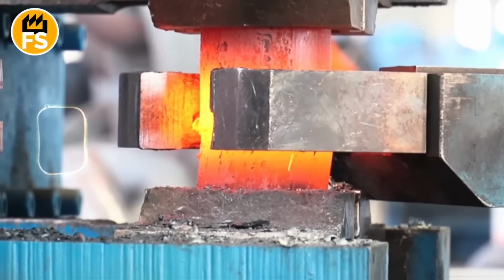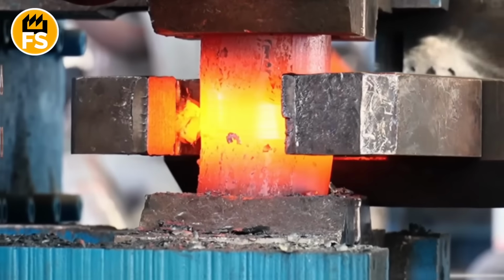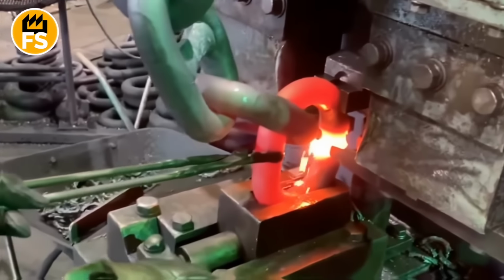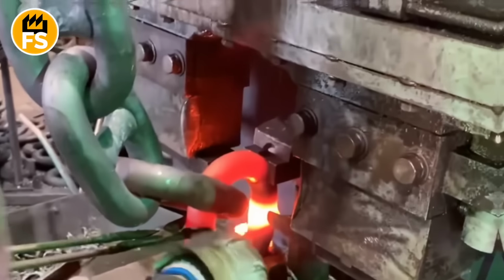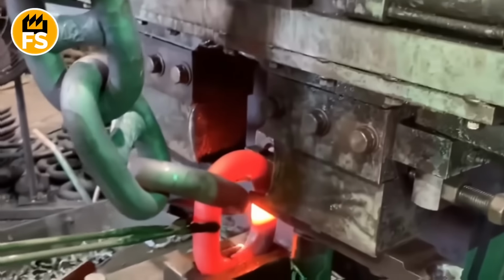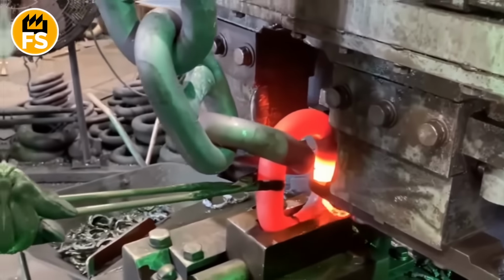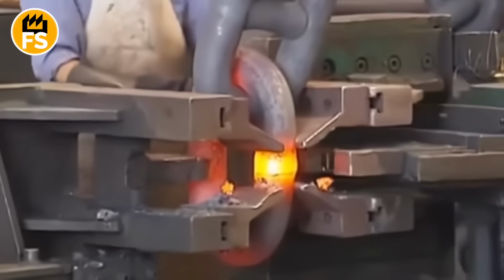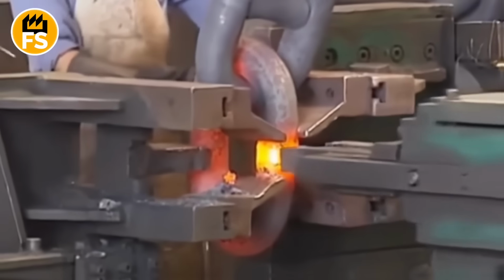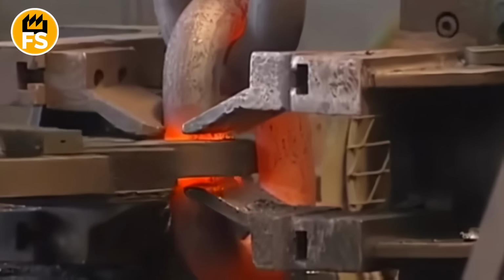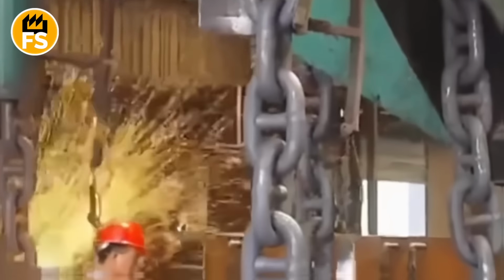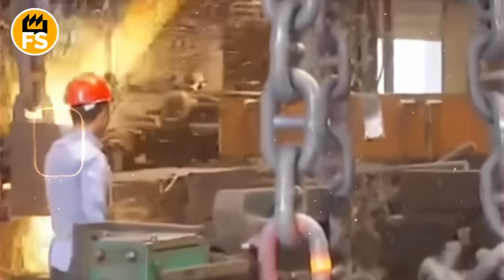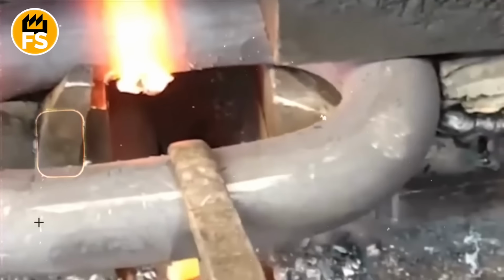The built-in deburrer does its job instantly while the metal's still scorching hot. Special cutting blades flow around the part's shape, whether it's a ring or a link, shearing away excess metal flush to the surface. Because the removal happens in the hot state, the metal doesn't experience the mechanical shock that comes with cold grinding. The smooth weld lets the chain or ring glide through pulleys and guides without friction or vibration, a must for safe operation over decades to come.